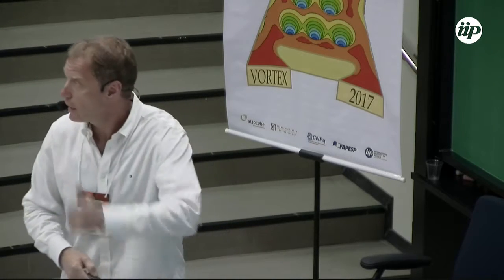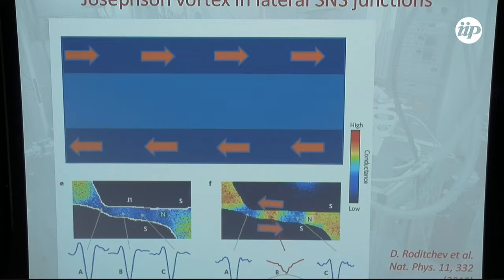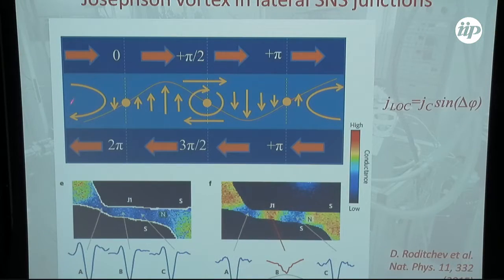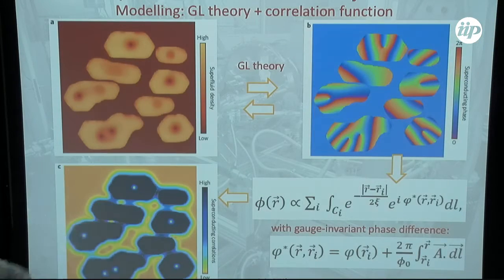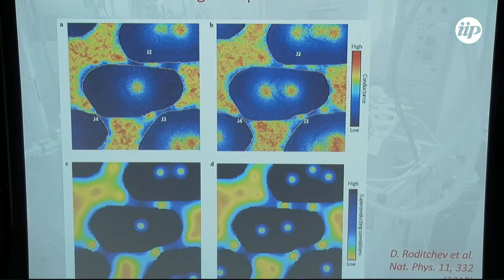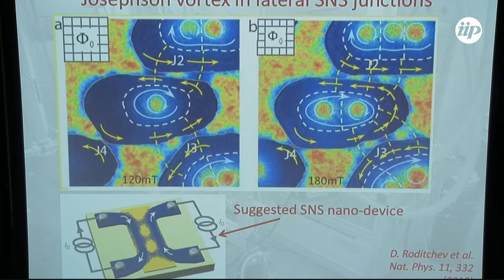In these islands, when you apply the magnetic field, you have Meissner currents which circulate in opposite directions along the two edges, because they circulate in all islands in the same direction. For these currents you have phase gradients, and necessarily you will face a situation in which you create a singularity of phase, and you get a destructive interference inside. We have fully consistent calculations of this, starting from the Ginzburg-Landau model and extending it inside, and with no free parameter we get complete agreement with the experimental data.